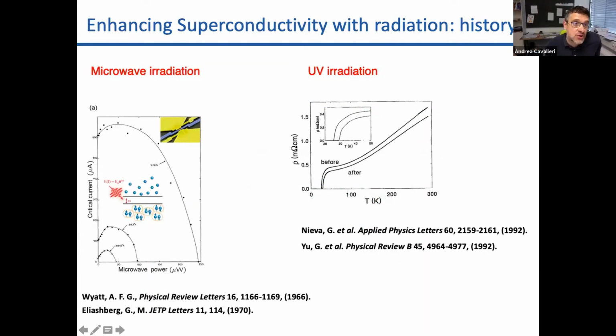Of course, this idea that you could try to use light to enhance superconductivity is not new. The most striking demonstration, in my view, dates back to the very early days of BCS superconductivity. This is work done by Wyatt and many people afterwards, who showed that in certain microbridges, they could irradiate a BCS superconductor with microwave radiation at frequencies lower than the superconducting gap, thereby changing the temperature and the density of quasiparticles above the superconducting gap, and somehow fooling the material and making it think that it's at a lower temperature than it is.